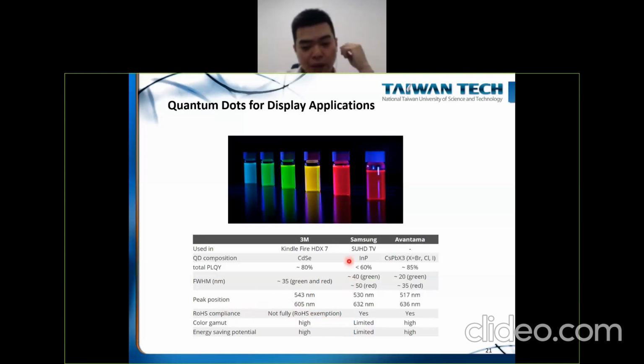But commercially used indium phosphide still has some problems. For example, its quantum yield is not as good, less than 60%, and its emission width is not as narrow as cadmium selenide. Also, because indium is a rare material, indium phosphide is more expensive than previously used materials. So people try to come up with new types of quantum dots, and one popular material which is widely studied recently is the perovskite quantum dot, a cesium lead halide material.